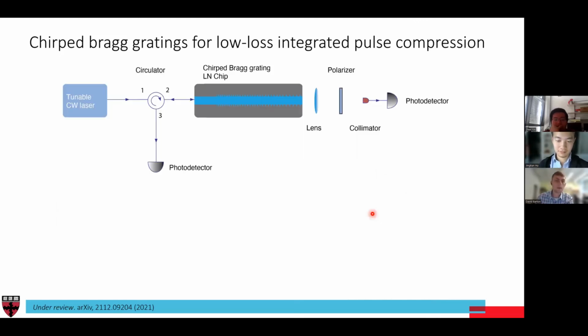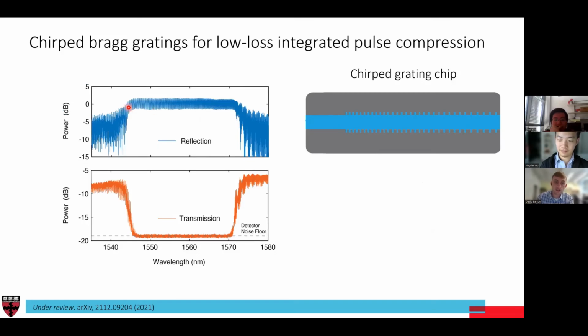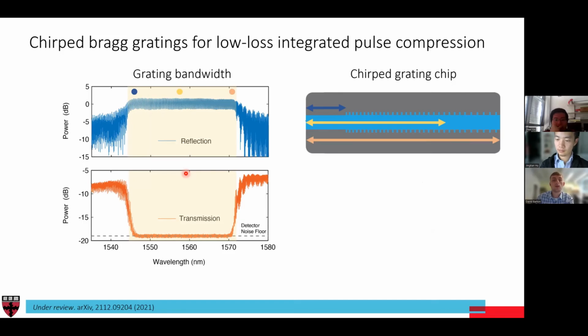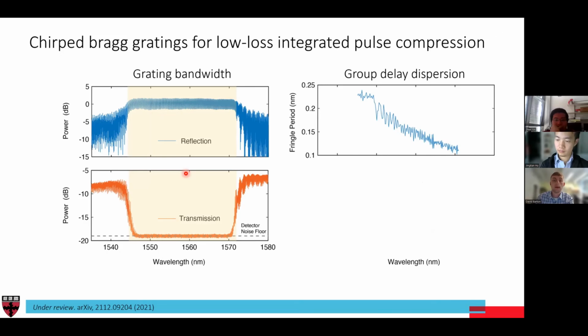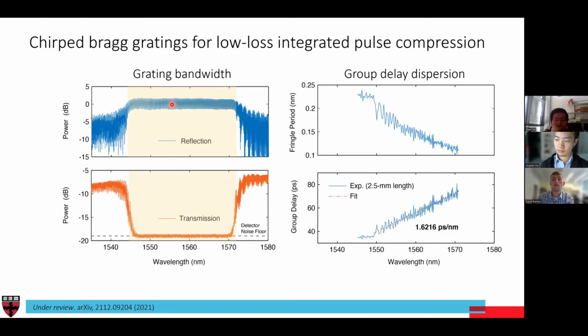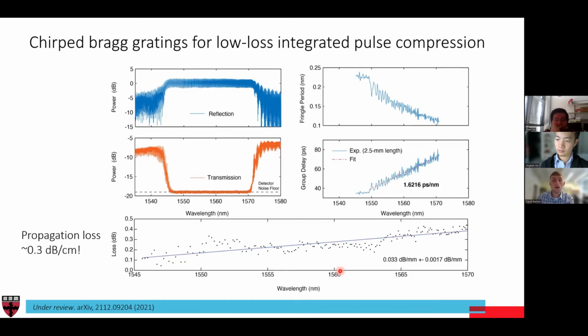And so given the timing that I see here, I'll very briefly go through how we actually characterize this. We made a series of devices and we're able to engineer the reflection spectrum right around where we have our pulse coming in, and we're able to engineer the dispersion. We can characterize this by fitting the spectrum. And what we find is that for something that's 2.5 millimeters long, we can get this dispersion to work quite well. We also fit the loss for this.